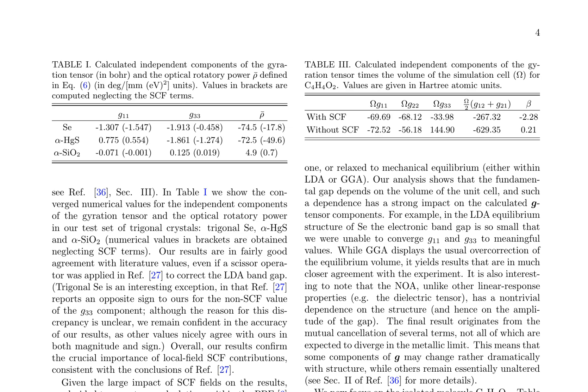The authors' first principles calculations are performed using the open-source ABINIT package and display remarkably fast convergence with respect to the main computational parameters. The study presents calculations of the gyration tensor and optical rotatory power in trigonal crystals and an isolated molecule using density functional perturbation theory. Calculations are performed within local density approximation, LDA, and generalized gradient approximation, GGA, parametrizations. Tables I and II show results for the independent components of the gyration tensor and optical rotatory power, demonstrating good agreement with literature values, even when neglecting self-consistent field, SCF, terms. However, the authors emphasize the crucial importance of local field SCF contributions, consistent with previous studies.